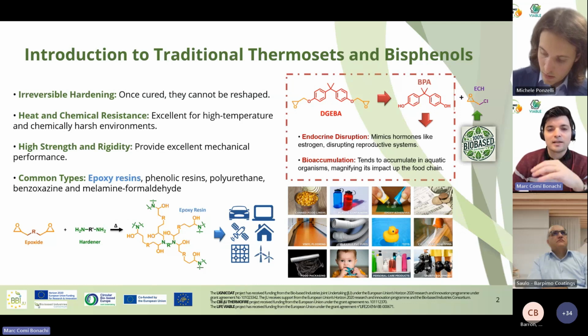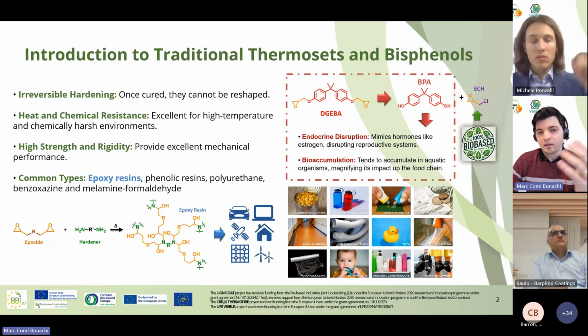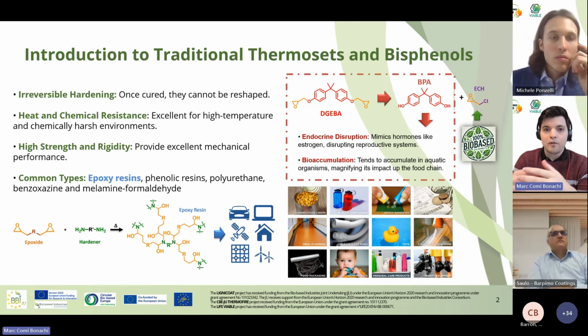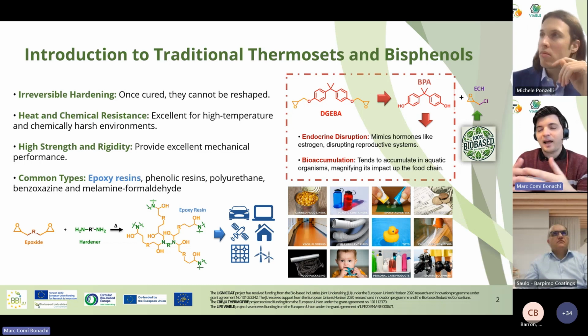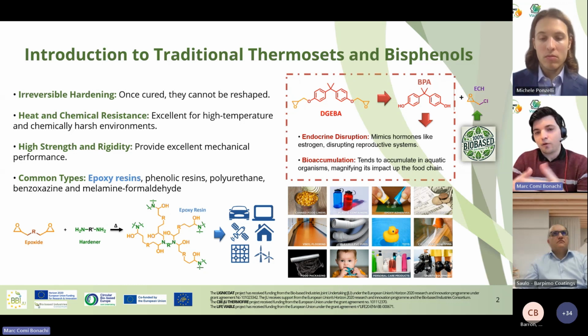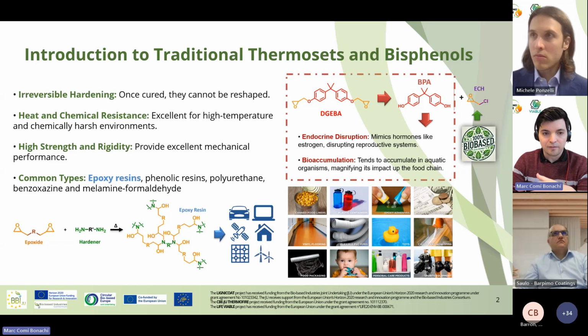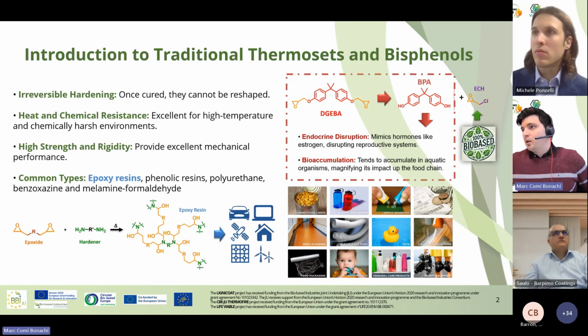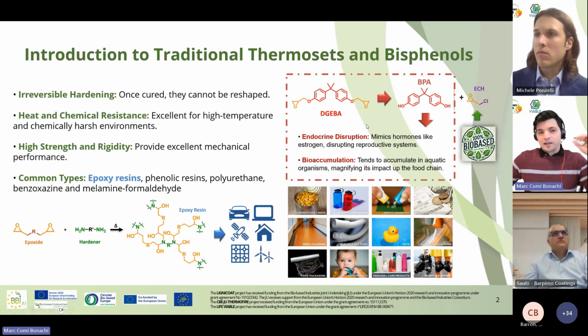But now we are hearing rumors also that in the next years, there is an increasing concern for all of these coatings made of epoxy resins based on bisphenol A that are in direct contact with water. That means piping of water, but also flooring. Because when we need to clean or wash the floor, we are using basic conditions that can remove part of this bisphenol A that is migrating and then dropping this bisphenol A in the ecosystem.